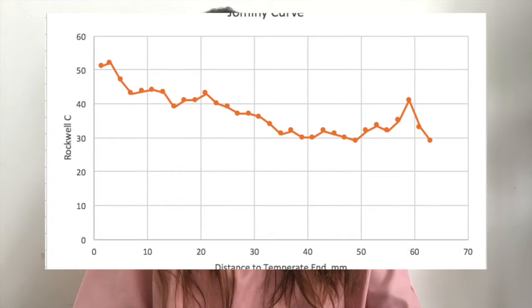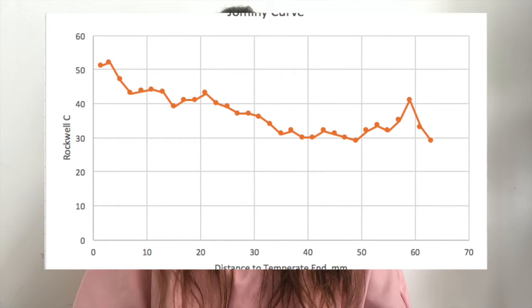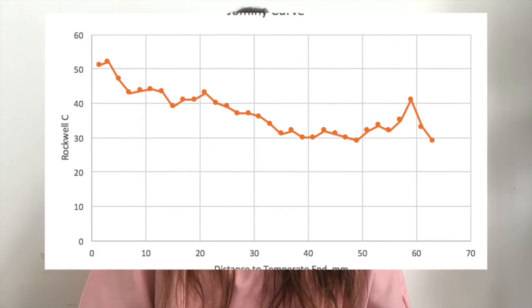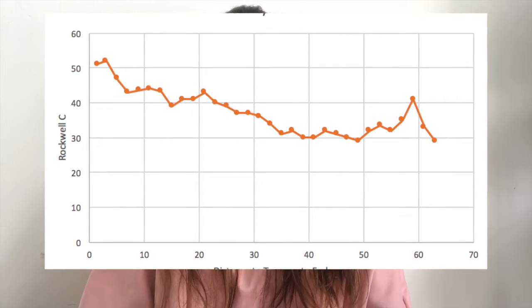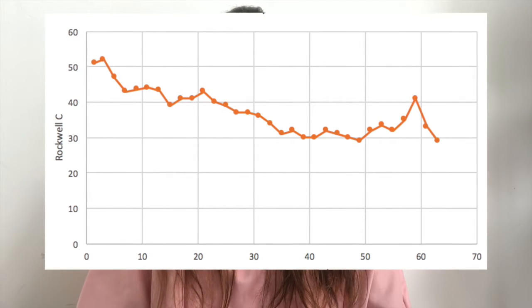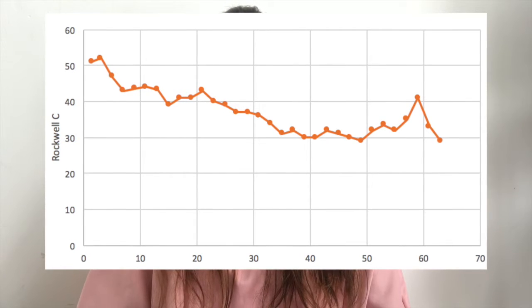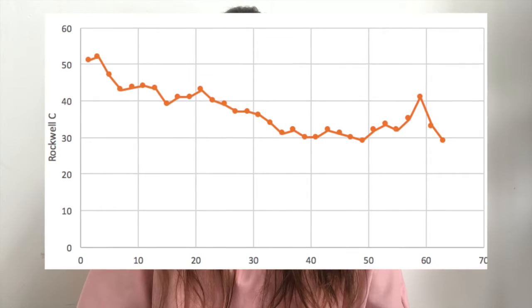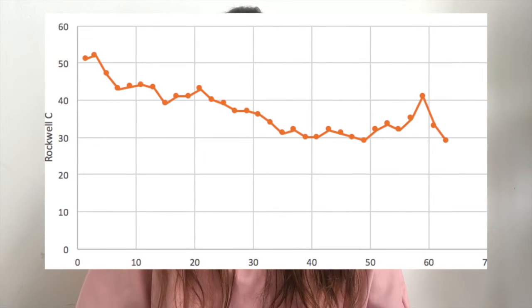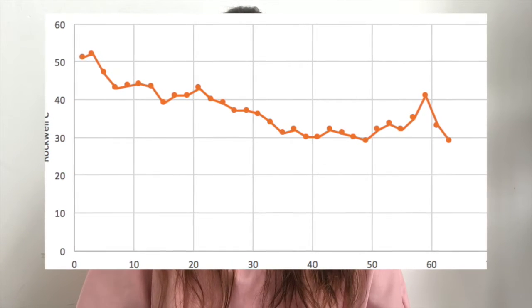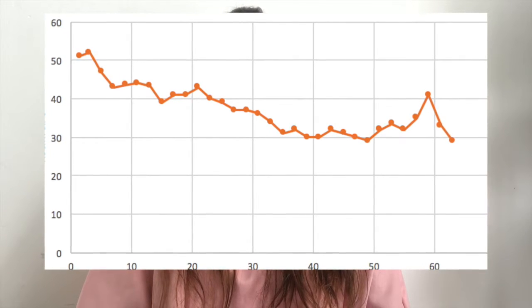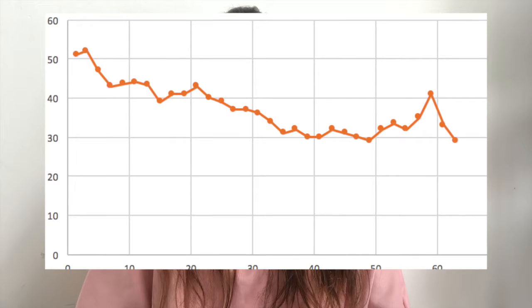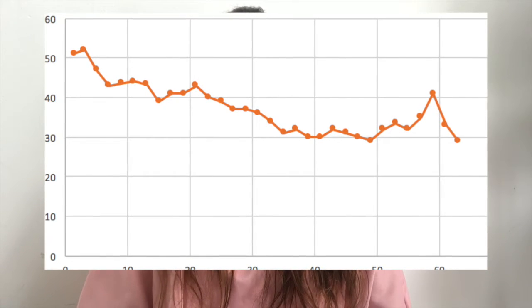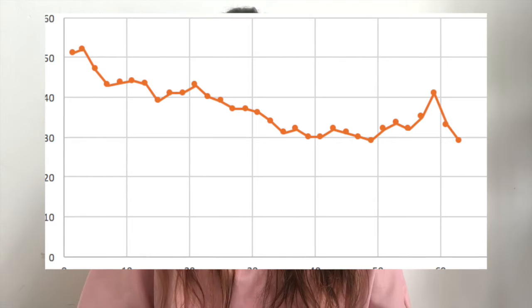We can see that in the curve the hardness decreases as the distance from the bottom of the Jominy test tube increases. This means that when we cool the test tube, the area that touched the water first cooled down faster and generated improvements in the mechanical properties. In this case, it improved the hardness. And the areas where the cooling took longer to reach, the hardness was less, and the properties, in this case hardness, were lower too.